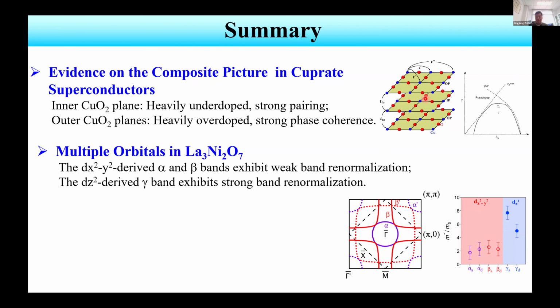This idea has already been borrowed to understand superconductivity in the nickelate samples 3-2-7. Because in this case we have two kinds of bands. One is from dx square minus y square, the other is from dz square. Some people propose that dz square has strong correlation and much stronger pairing strength, but dx square minus y square can act as the high coherence temperature. By putting the two together, there's some competition and interaction between them, which may also give rise to a high Tc in this case.